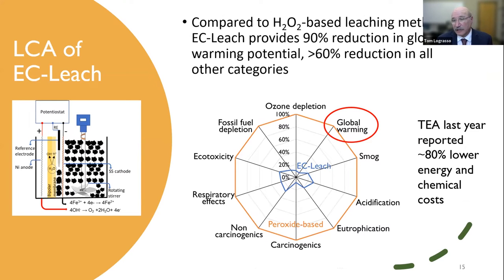So this is a life cycle analysis of this electrochemical enhanced leaching process where we use iron as a reductant in the process to assist leaching. The alternative is to use peroxide. That's what's used today, a hydrogen peroxide-based leaching method. With EC leach, we attain the same sort of leaching capabilities, but the number of factors are reduced significantly. For example, global warming potential is reduced by 90%, and greater than 60% in all categories.